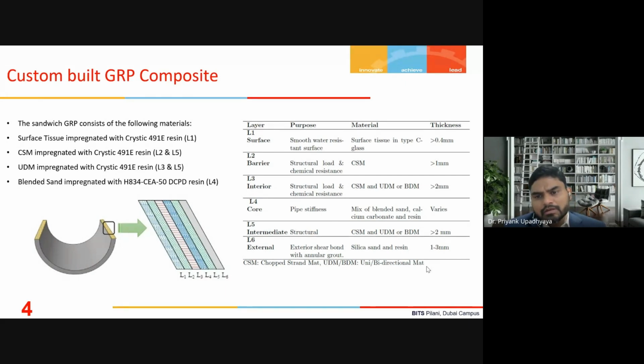Then we have an intermediate layer, which is again made of chopped strand mat or UDM or BDM layers. This is again slightly higher than 2 mm. And at the outset, we have the external layer, which is made of silica and resin, around 1 to 3 mm.